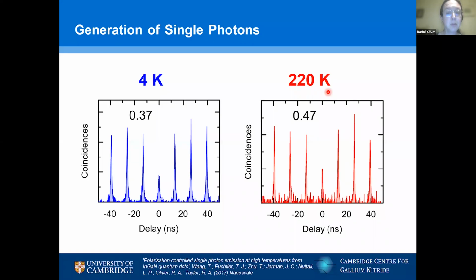We still have a dip at 220 Kelvin. It's just not below 0.5 in terms of the comparison between the surrounding peaks and the central peak. So yeah, okay, it's a single photon emitter, fine. But in applications, these extra photons, which are contaminating the single photon stream, are a problem. They are probably from that fragmented quantum well layer that I showed you when I explained how the growth works, other regions of material not in the quantum dot, but emitting at the same wavelength.